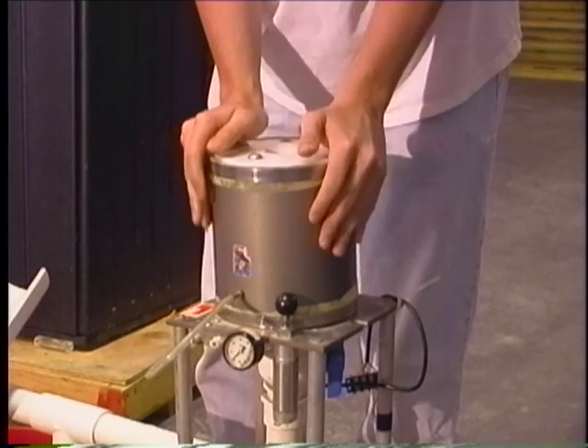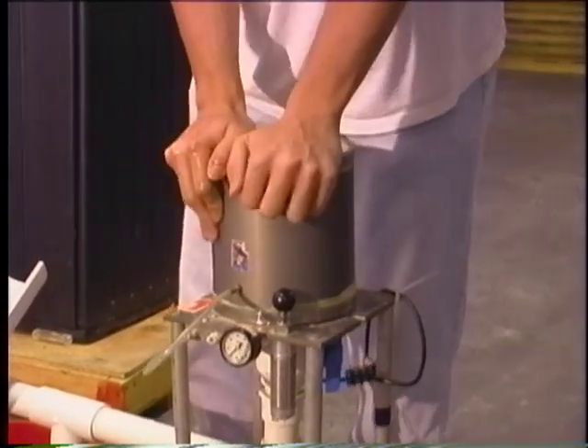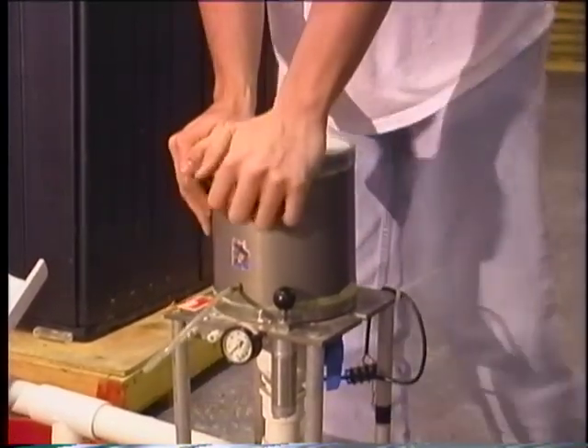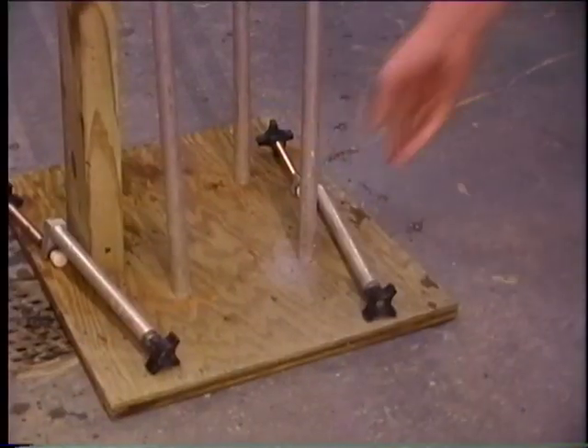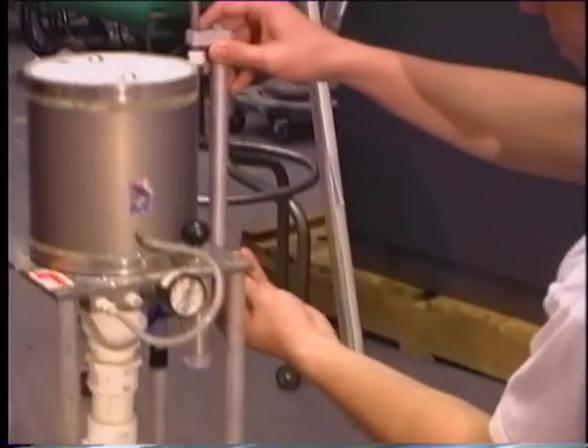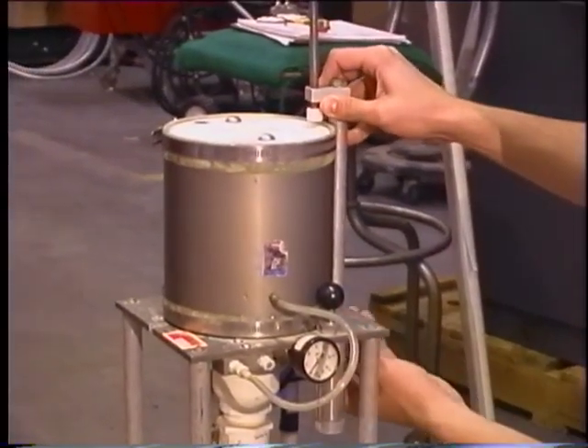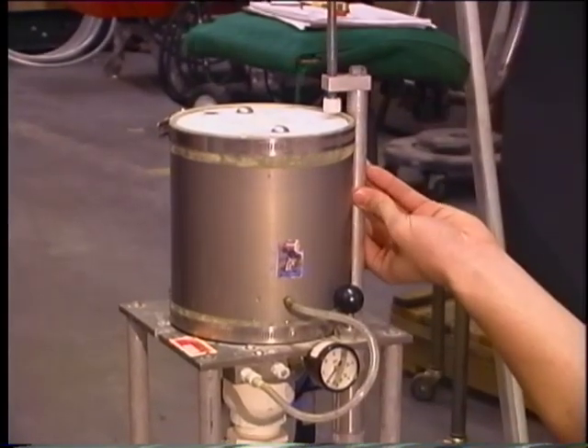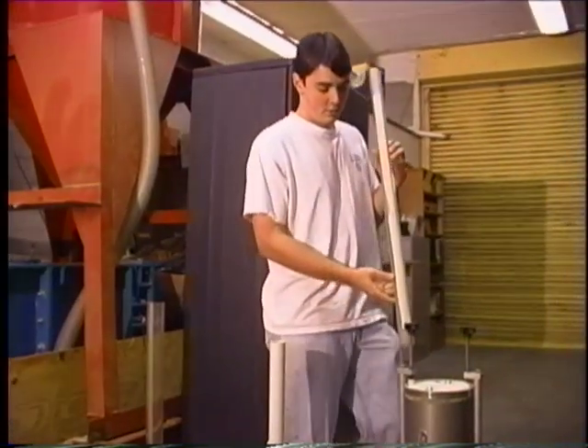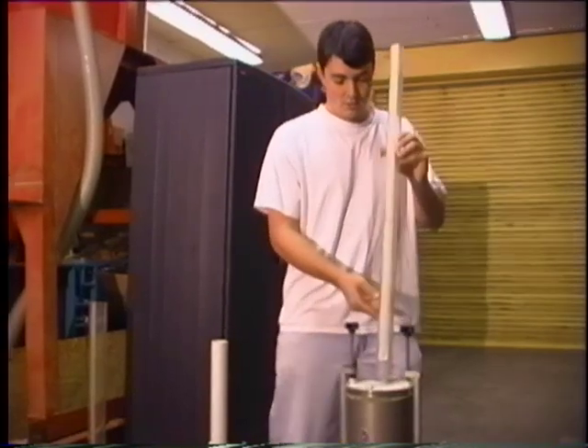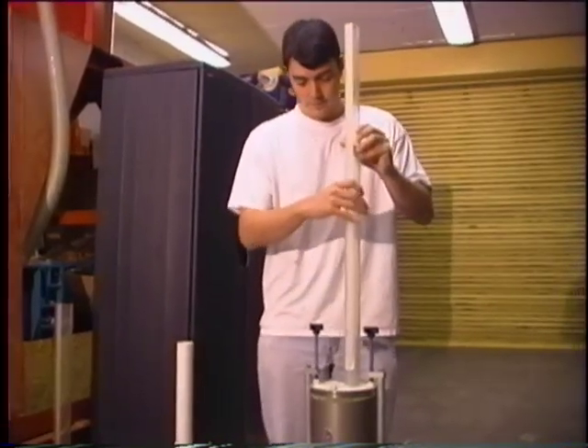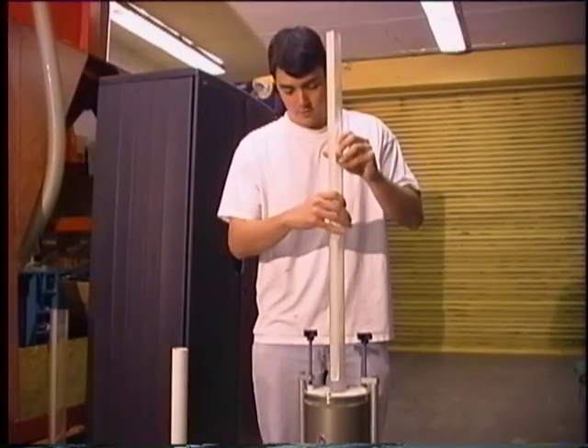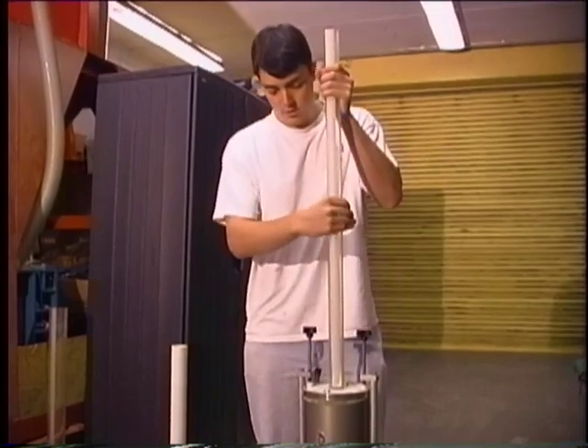At this point, the chamber is placed over the top of the specimen and secured to the permeameter base with C-clamps. C-clamps are necessary to prevent pressure from pushing the upper cap out of the chamber. Place the tube that measures the height of the water into the upper cap. It must be seated past the O-ring and pop into place. The tube is 36 inches in length.